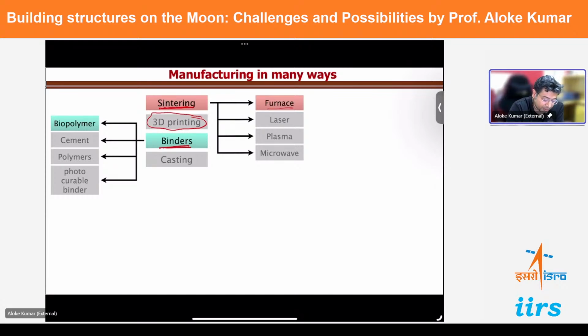In sintering, we have tried furnace sintering. Sintering is a technique where you make bricks by heating them together. So you put a brick like this, cast, into an oven, and the oven goes to a very high temperature, close to 1,000 degrees Celsius, and then the particles start to adhere to each other. By the way, when you saw the footprint of the Apollo astronaut on the surface, that material is just loose sand, and the particles are just sticking to each other because of friction. So in sintering, you heat it at a very high temperature such that the bonding becomes very, very strong. Particles migrate, atoms and molecules, so at the edges they fuse together and become bonded. We have reached strengths greater than 20 megapascals that way. I just told you the strength of a typical house brick is 5 to 20. So we have reached strengths greater than that with sintering.